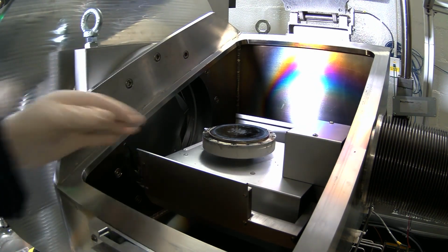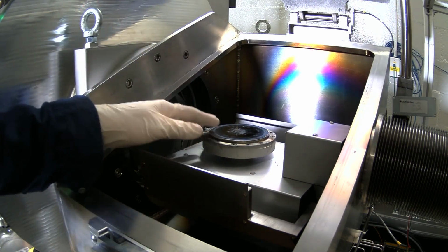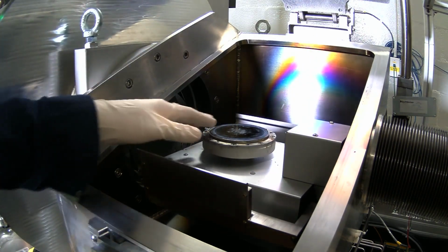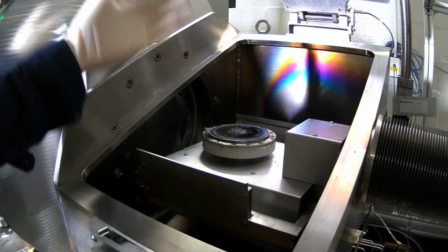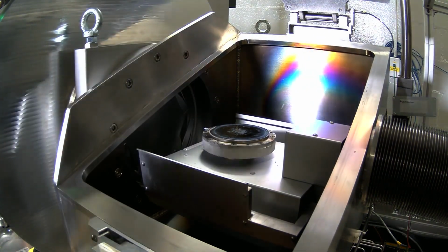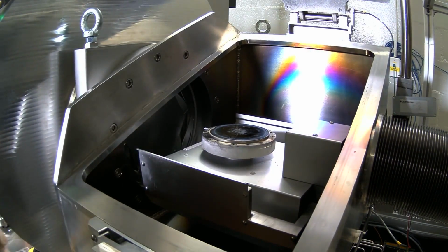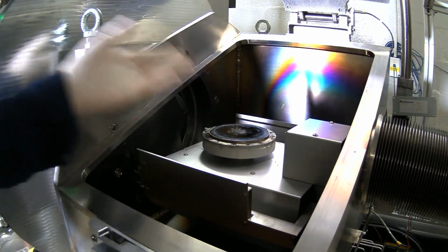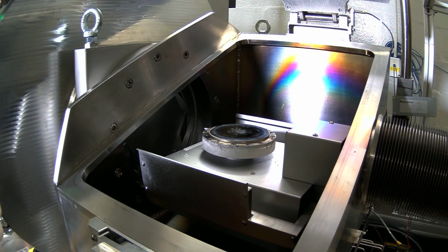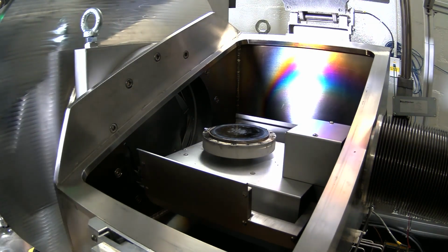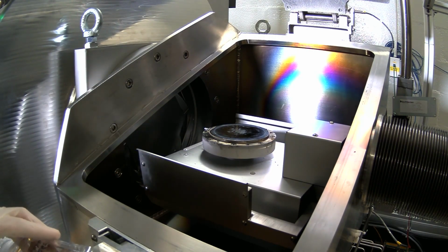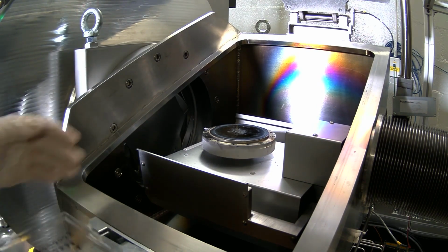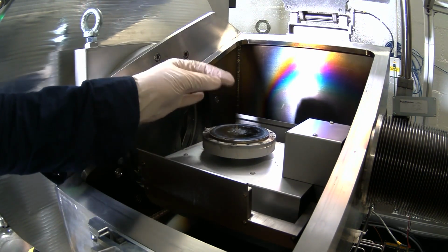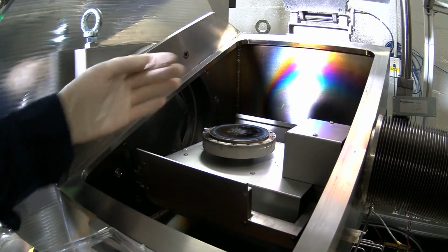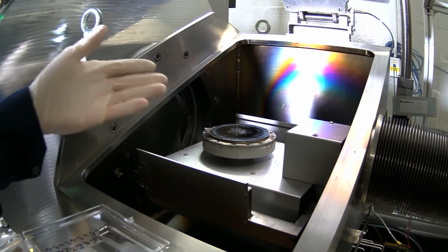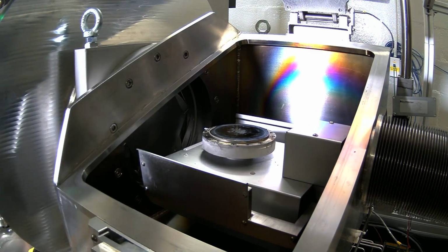You could also use a stainless plate. I wouldn't recommend an aluminum plate because it's going to etch through it very quickly, but there are options there. Silicon is a very cheap and convenient thing to use, so we just use test grade silicon wafers. This in the center is actually a SEM sticky, the standard SEM mount. That's nice because it provides very good thermal contact and mounts the piece flat, and there's no exposed organic material that can be etched.